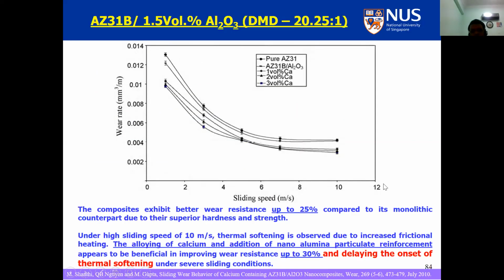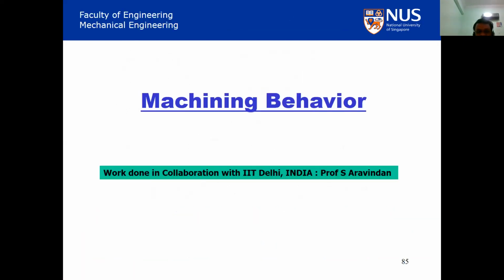Sliding is another engineering application that is commonly seen in many applications: automotive industry, tracks, railways, and everything. So putting nanoparticles like Al2O3 also helps AZ31 to improve its tribological performance, or the wear performance, by up to 25%, and that is with only 1.5 volume percentage of Al2O3. If you want to increase more, you put more calcium, 1 to 3%, you get another 25% increase. And what you are getting now is almost like a 50% increase. So 1.5 times the life cycle.